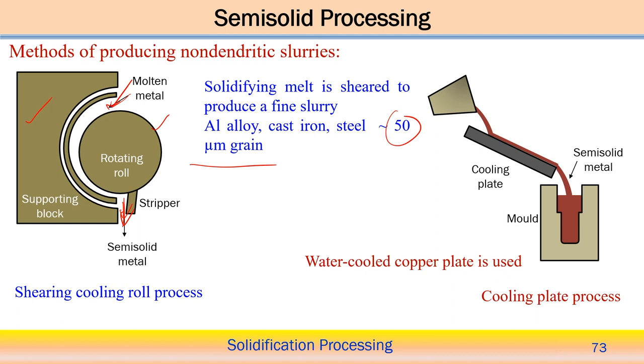Now there is another semi-solid process, in which a water-cooled copper plate is used. This is the liquid metal. Liquid metal is poured on the cooling plate, which is water cooled and has high conductivity, made of copper. Yes, a copper plate can be used here because, as we know, in continuous casting and other processes we usually use copper plates.